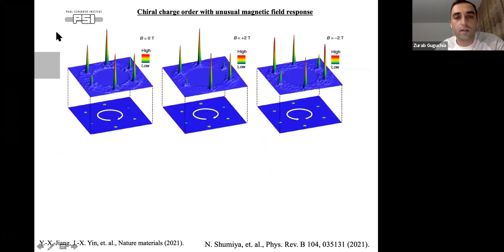And then later on, STM experiments have shown that the system exhibits a 2x2 charge order, an isotropic charge order, which is consistent with a breaking of translational symmetry along the a and b directions. And this is a Fourier transformation of the real space spectra. They could see some kind of intensity differences between these three charge order wave vector peaks, and these differences in intensity were denoted as a chiral charge order. And when you apply the magnetic field, they can also switch the intensities of these different Q vector peaks, so you can tune this intensity by magnetic field. And I think Jashin talked a lot about this during his seminar.